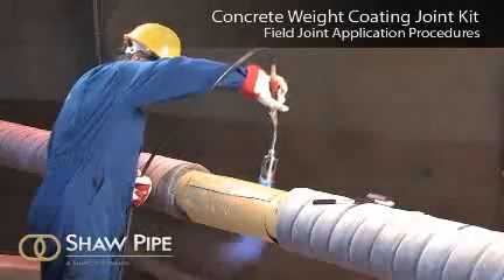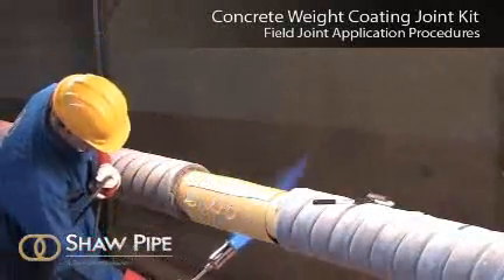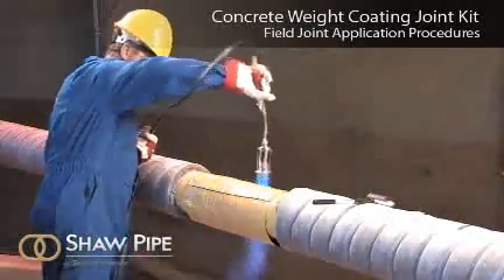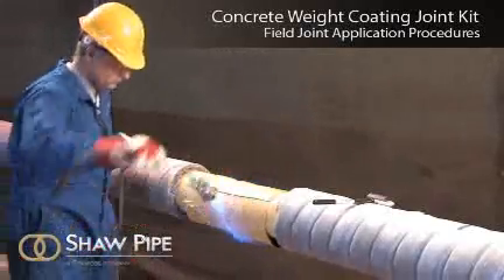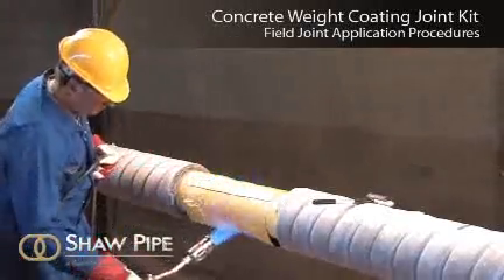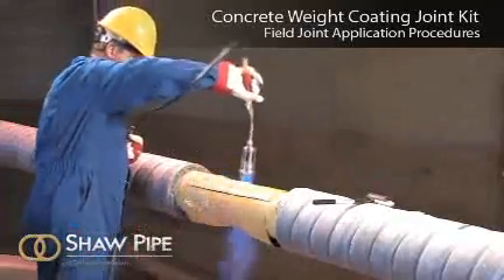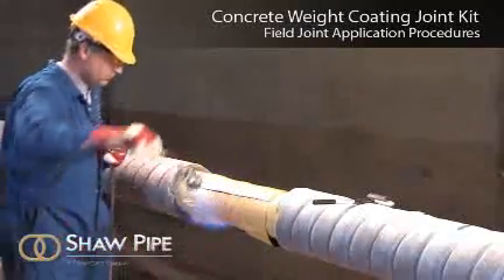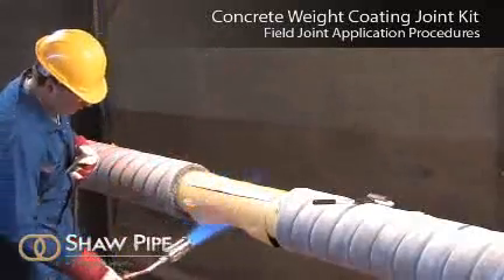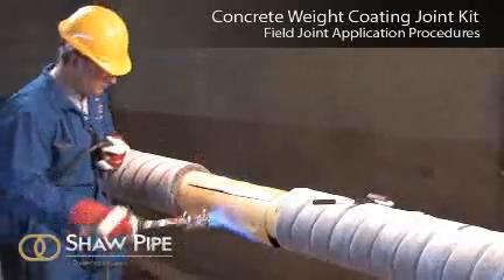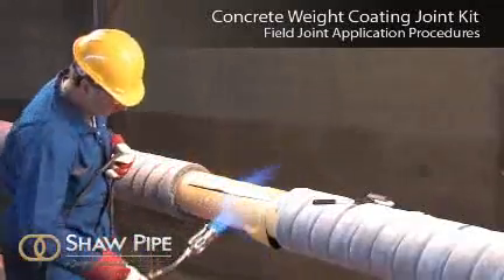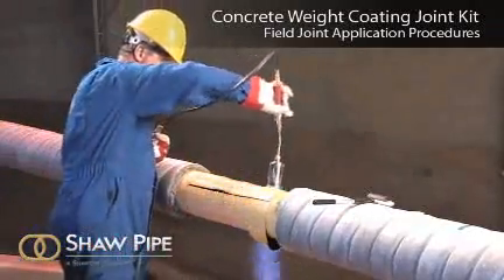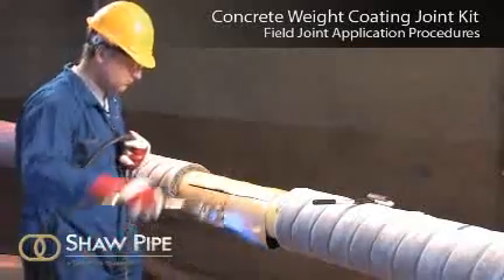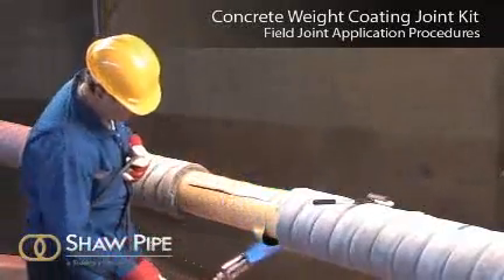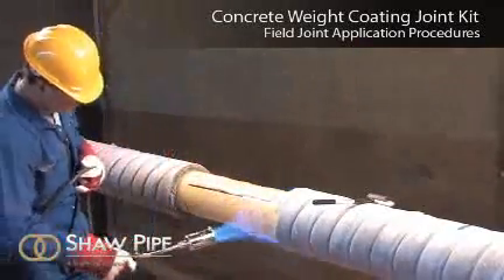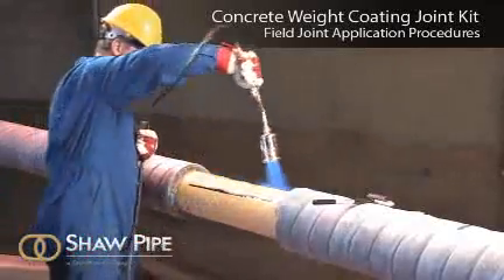Using the torch, begin at the center of the sleeve and heat circumferentially around the pipe using broad strokes. If using 2 torches, the workers need to be on opposite sides of the pipe. Continue heating from the center toward one end of the sleeve until recovery is complete. In a similar manner, heat and shrink the remaining side. Shrinking has been completed when the adhesive begins to ooze at the sleeve edges all around the circumference. Finish shrinking the sleeve with long horizontal strokes over the entire surface to ensure a uniform bond.